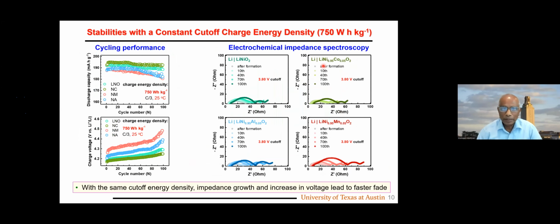So the best way to compare is to have all of them subject to the same cutoff charge energy density, that is 750 watt-hour per kilogram, on the cathode level. If you do that, then the trend is exactly the opposite of what you saw in the previous plot, meaning LNO and NC in fact show better cyclability than the manganese and aluminum doped. And why is it? We have looked at the impedance, as we see here. Manganese doping leads to larger impedance, and that also leads to an increase in voltage and polarization. That's why the cyclability is falling off.